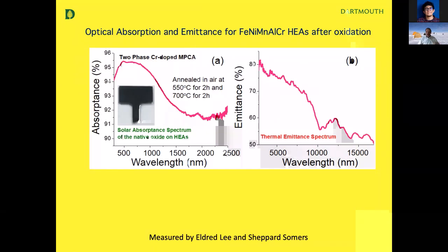For concentrated solar power, you need to absorb sunlight, so we measured the optical absorbance over a wide range, so this is beyond the optical spectrum here. And the interesting thing is that the oxide on the surface absorbs greater than 90% of light over this whole spectrum, which is a very high value actually. It also has a pretty low emittance as well. So there's great interest in this, and we're working on a project on concentrated solar power, where we're looking at these high entropy alloys as tubing materials for concentrated solar power applications.